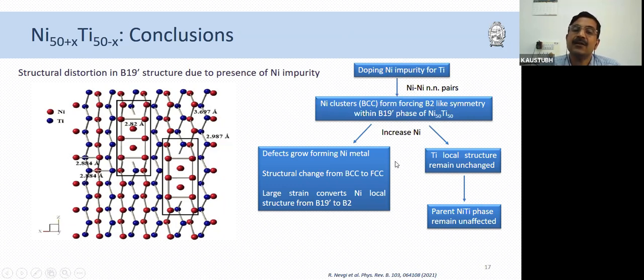With increasing nickel concentration, the titanium local structure we found to remain unchanged. So we can say that the parent nickel titanium, or the nano domains, or those structural domains of nickel titanium are unaffected. But as there are these defects, which are initially body-centered cubic, eventually with increased nickel concentration, there is a structural change of this defect symmetry from body-centered cubic to face-centered cubic. And this is the reason why we have interruption of the long-range order. This defect causes the interruption.